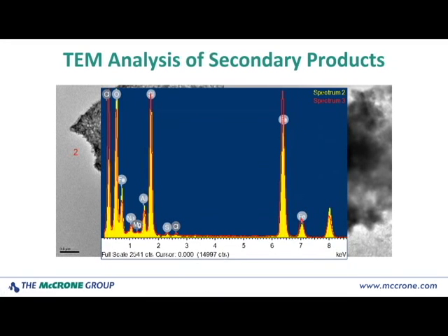And analysis of several areas showed that these actually had consistently different compositions. This was an iron-containing API, and the products that I found were high in silicon and also high in iron, but consistently showed two different silicon to iron ratios, depending on whether the morphology was the needle-like structure or the more fluffy or amorphous looking structure.